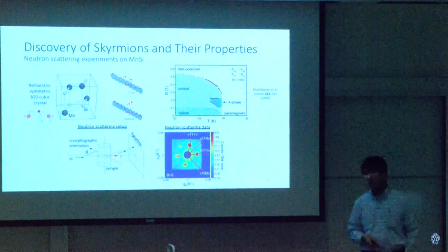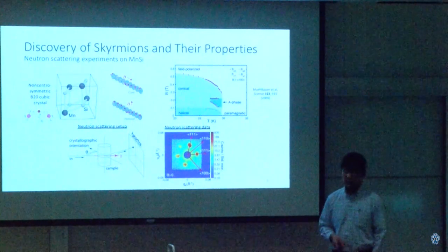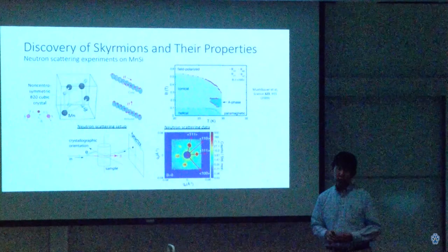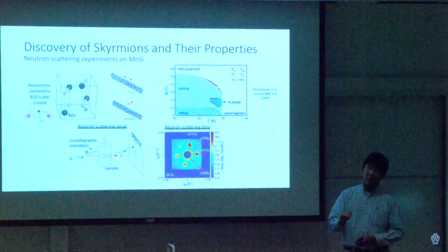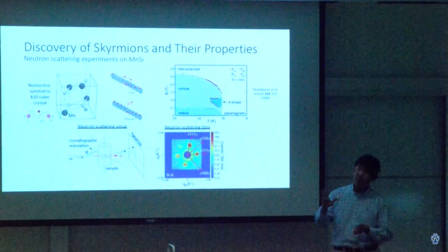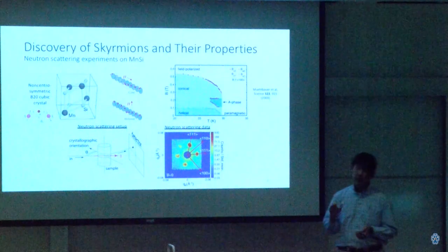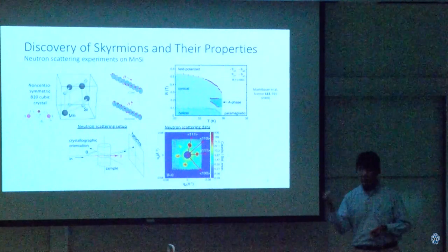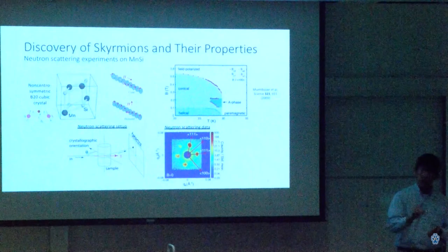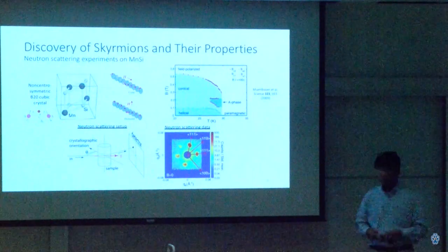Question. Yes. Are the neutrons monoenergetic? Yes. They're monoenergetic, and they're what are called thermal neutrons, which means that they had roughly 20 to 25 meV of kinetic energy. Just slow enough to make it through the material and interact with something.